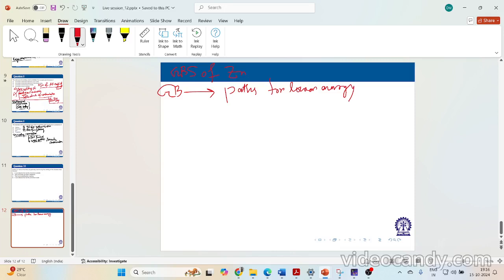So that is grain boundary segregation. And what will be the effect of zinc segregation during welding? There will be this defect called liquid metal embrittlement, what I was talking about at that time. So zinc in its liquid state penetrates the grain boundaries of the steel at high temperature, and that will lead to the formation of cracks along the grain boundary path. So liquid metal embrittlement is also called intergranular cracking.